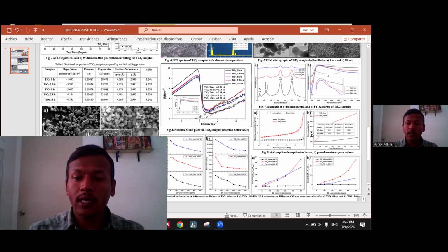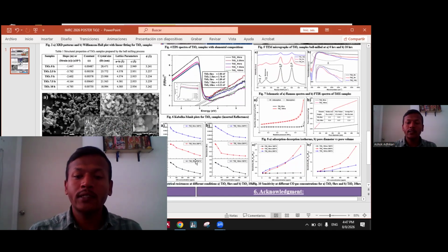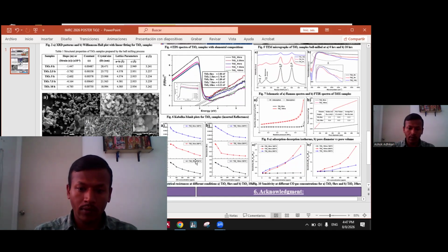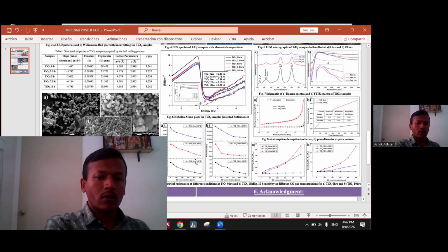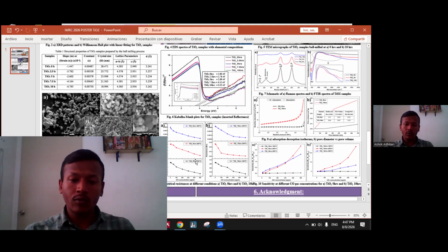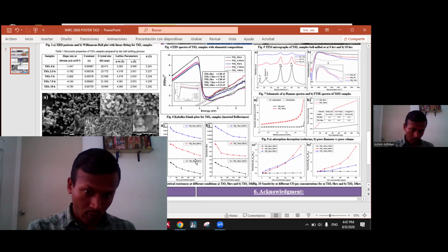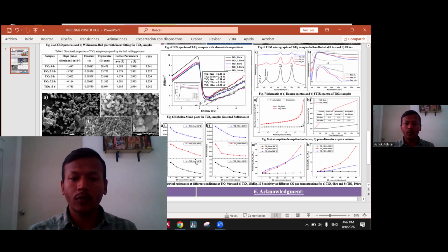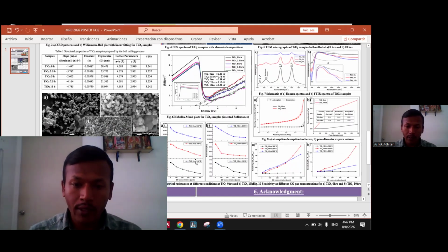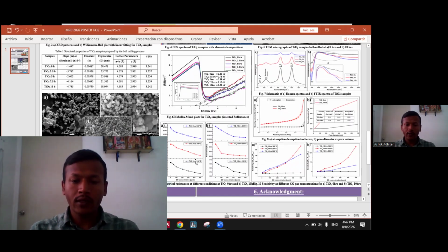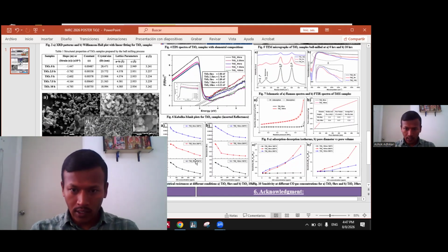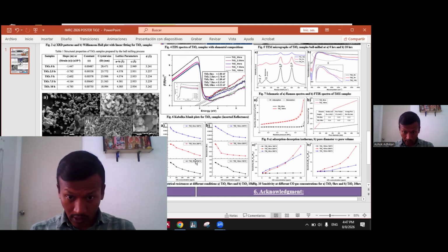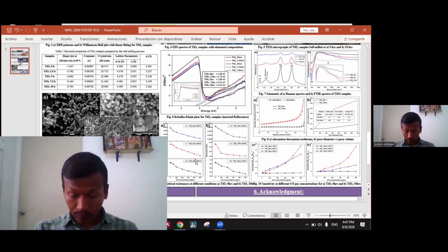And finally, we have checked the gas sensing properties, and we have calculated the electric resistance at different conditions. Initially the sample is taken in air, and after that it is exposed to CO at various concentrations from 0 to 500 ppm. So we have checked the resistance of the samples, and the sensitivity is calculated as the difference between the electric resistance of the samples.